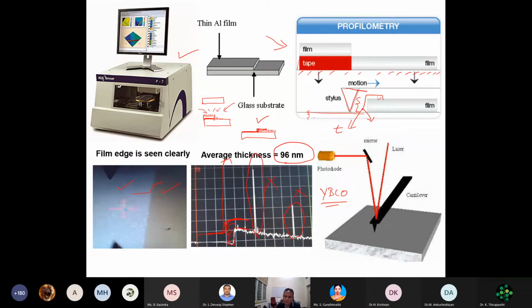And remember that because I'm scribing with a sharp tip, this may not be suitable for a soft material, because it will damage the material itself and you cannot estimate the accurate thickness. So the stylus profiler is suitable for hard materials, not for biological and very soft materials.